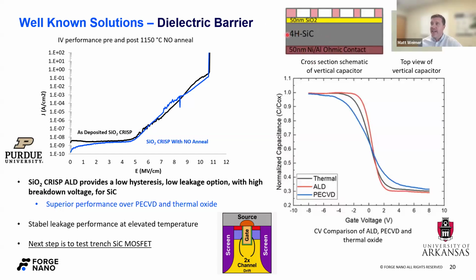We have some ohmic contact, the silicon carbide, and then 30 to 50 nanometers of the silicon dioxide ALD. And then we have different pad diameters. This is a top view of that contact. Maybe jumping back into the CV sweeps here, now we're comparing just a thermal oxide versus ALD silica crisp versus a PECVD. One of the things that really stands out is how vertical that sweep is for the ALD film. It certainly looks better than all three. And then, not shown here, but when we looked at the hysteresis of these films, the ALD film performed the best of the three.